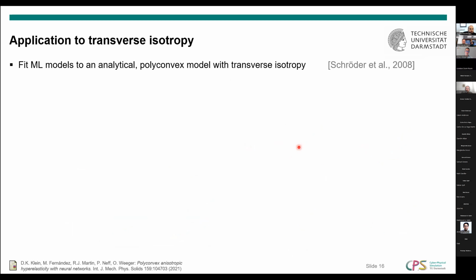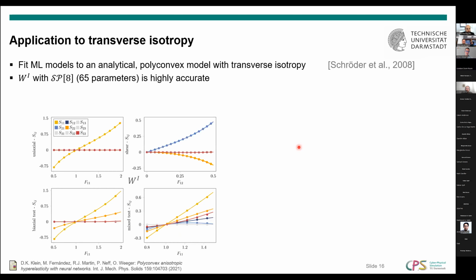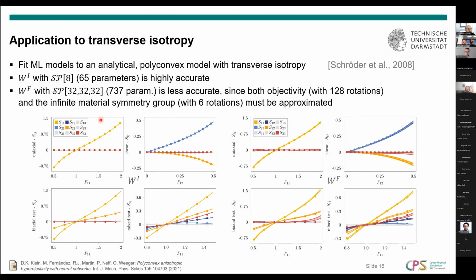Now, if we go to a little simpler material behavior, here we have transverse isotropy, where we generate data from an analytical model. Then we fit the invariant-based neural network model, where now we know exactly which invariants to use. Here we get an excellent fit of the data with a neural network that has just 1 layer and 8 nodes inside the layer.